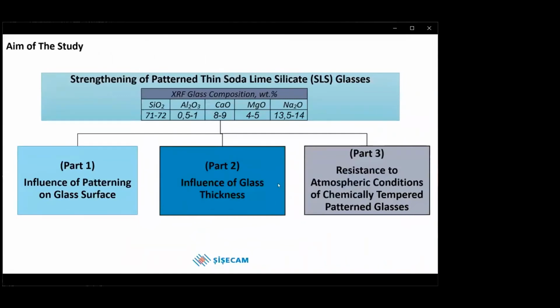In our project, we have completed our research on three main topics. We have studied with a 2 mm soda-lime silicate glass composition. First, we examined the chemical tempering behavior of patterned glass and compared it with the float glass. Then, we examined the influence of glass thickness on the chemical tempering process. Finally, the resistance of chemically tempered patterned glasses against atmospheric conditions was examined.